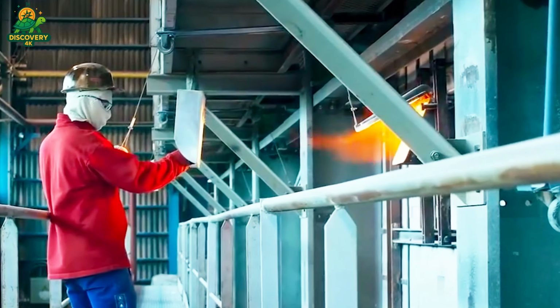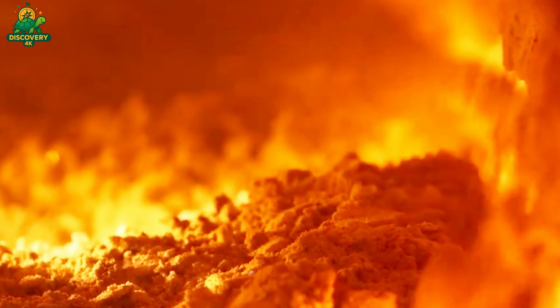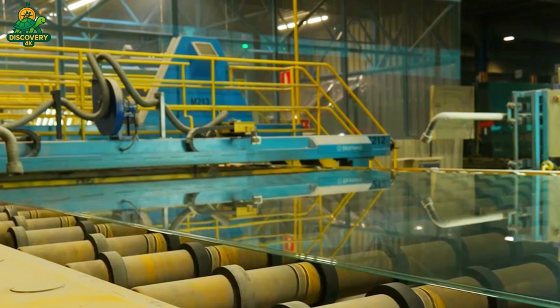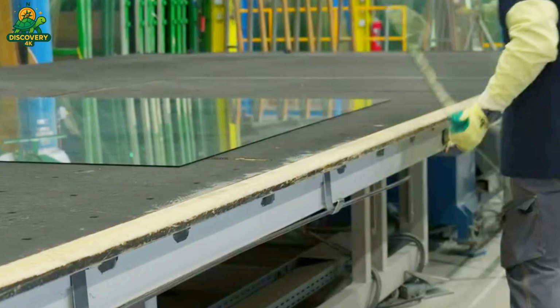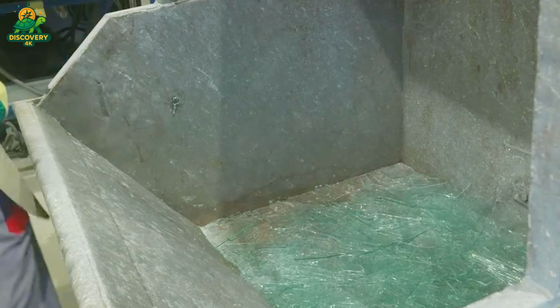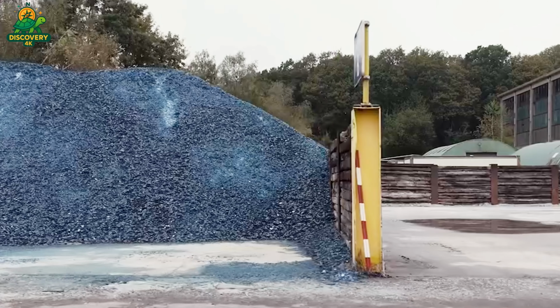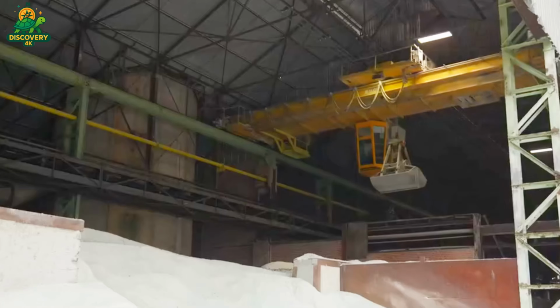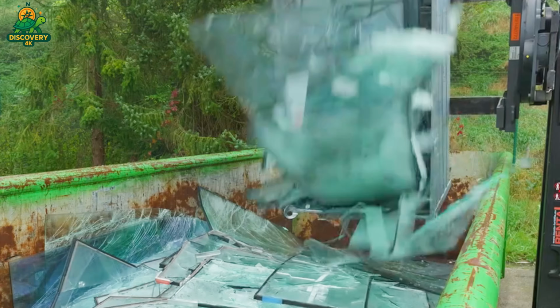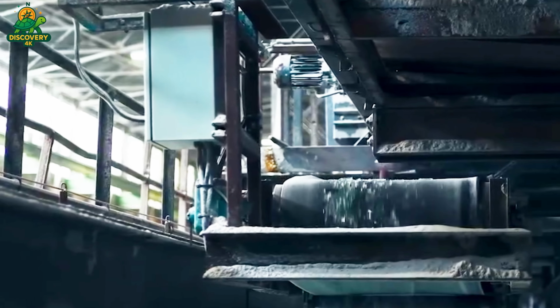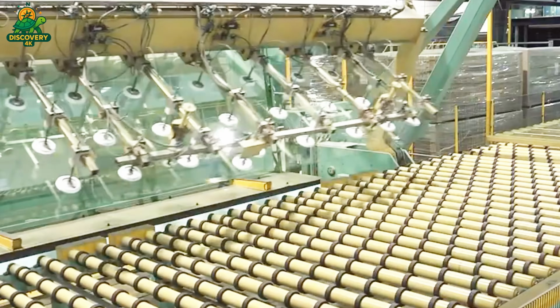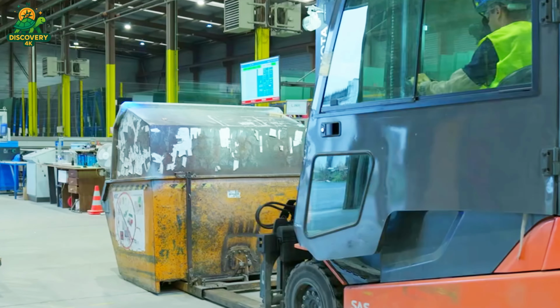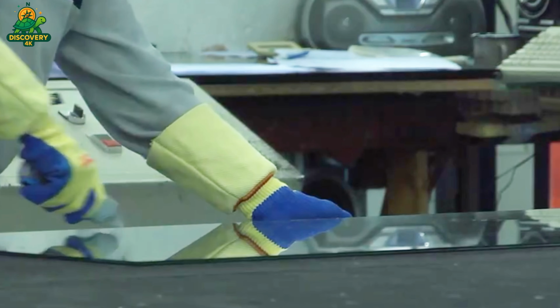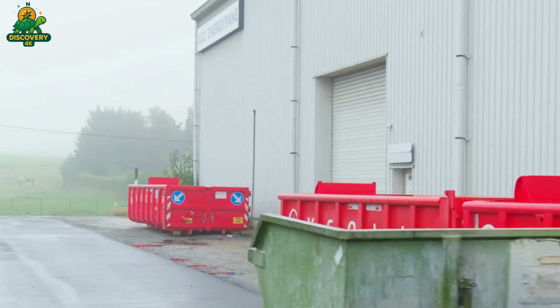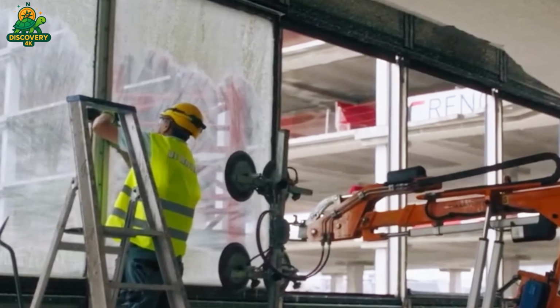Flat glass. For flat glass, the factory uses something called the float process. Here's how it works. The molten glass flows onto a bed of liquid tin. Yes, real molten tin, because glass floats on it like oil on water. The glass spreads out into a smooth, flat sheet as it glides across the tin. It's kind of like watching pancake batter settle, but glowing hot and way more precise. The sheet cools just enough to hold its shape and then rolls forward like a glowing ribbon. Perfectly flat, perfectly smooth.